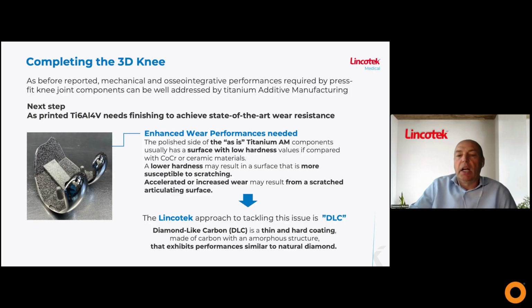The polished side of the as-is titanium additive manufactured components is a surface that can be absolutely smooth, however low in hardness if compared to cobalt chrome or ceramic materials. And a surface that exhibits lower hardness may result in a surface that is more susceptible to scratching. Accelerated or increased wear may result as a consequence of scratches in the articulating surface.